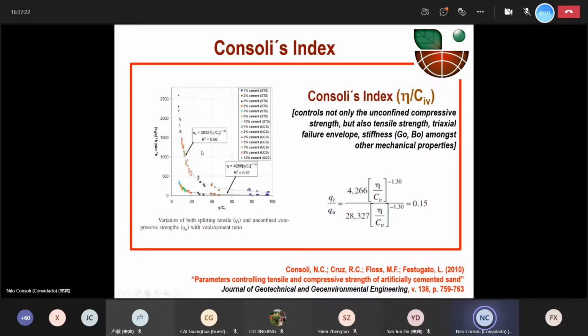And the equations are quite similar. Even the power here is the same. So if you divide the full equation here for a unique sand, but with different amounts of cement and different dry densities, in the end, you get a scalar. And this scalar is the relation for this material, for this cement. But what is interesting, and that we have shown later, is that for each soil and each kind of binder you have specific values that vary between 0.10 and 0.18. So each material might have a different one inside this range.